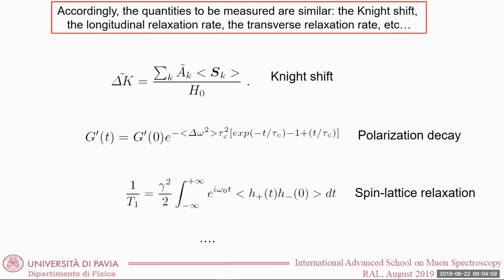Given this, at the end of the day, the quantities that you are measuring with nuclear magnetic resonance and MUSR are rather similar. For example, you can measure a shift, namely the shift of the Larmor frequency that you have in your material with respect to the vacuum. You have a time evolution of the nuclear or muon polarization, which is determined by basically two quantities. One is the mean square amplitude of the field fluctuations, and the other is the characteristic correlation time, tau c, of this fluctuation. This is the same for NMR, for beta NMR, and for MUSR. You can measure the spin lattice relaxation rate, and this is what you can measure both in NMR and, if you want, with a longitudinal experiment in MUSR. So at the end, there are many similarities.